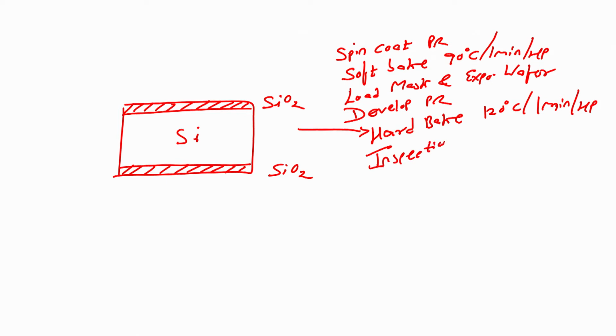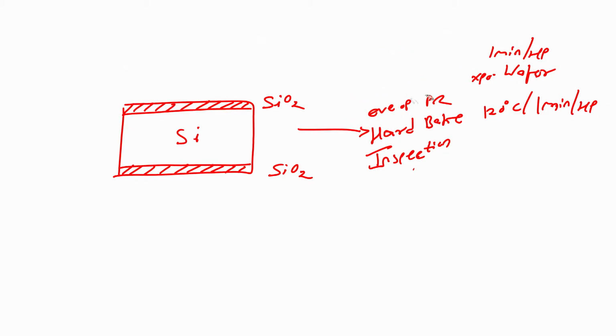Inspection is done using a microscope, right. So, these are the steps for your photolithography. Once I perform photolithography, I will create a window into the silicon dioxide and then I will etch the silicon through that window. What does that mean? If I perform photolithography, I will be creating a wafer. This is an oxidized silicon wafer, and I will protect it with photoresist in all the area except in the center. So, this is my photoresist, and as you can see there is a window, right.